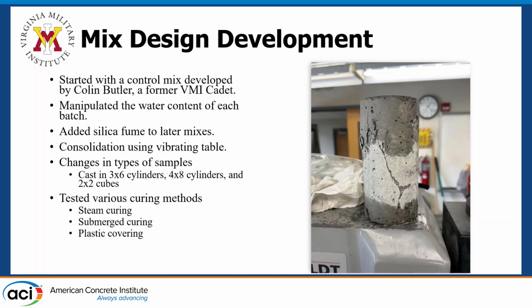So I actually went with a rather unique method of curing, steam curing. So going back to that apparatus that I created, submerged curing. So I actually kept concrete samples in buckets of water for 28 days straight. Once again, going down to the lab every time, refill that. It was a great feeling. And then I just used plastic covering in an ambient room temperature.